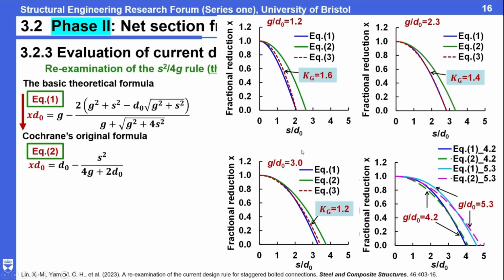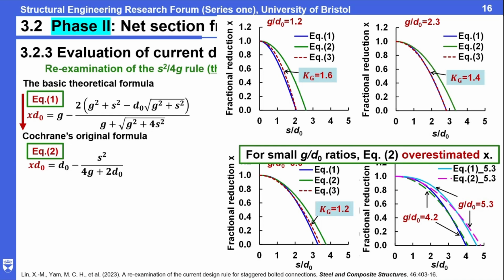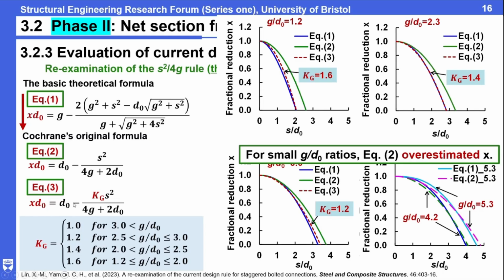When we look at the background, we first compare these two equations to see whether the determined x value is the same. When g/d0 is lower than 3, we found that the blue line, from equation 1, is exactly the x value from the complicated equation, and the green one is from Cochrane's equation. We found that blue is always lower than green. It means the x value based on equation 1 was overestimated by the green one, right? So we needed to calibrate a little bit. That's why we propose a factor kg to account for the effect of g/d0 on the calculation of x. The dotted red line is after calibration, and we calculate the x value. You can find that this is consistent very well with the results from the originally complicated equation.